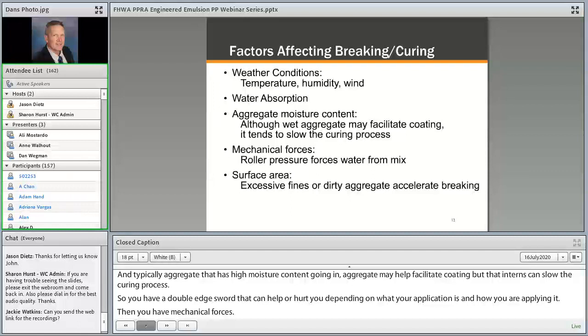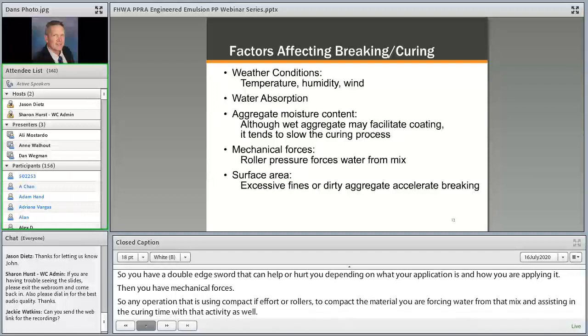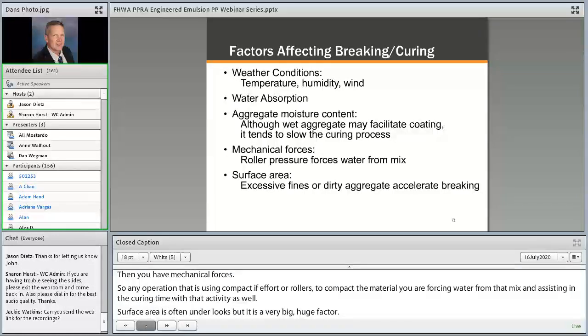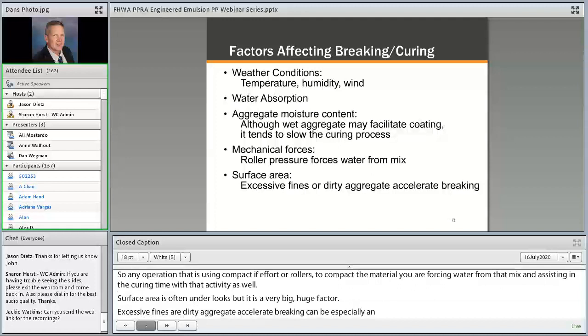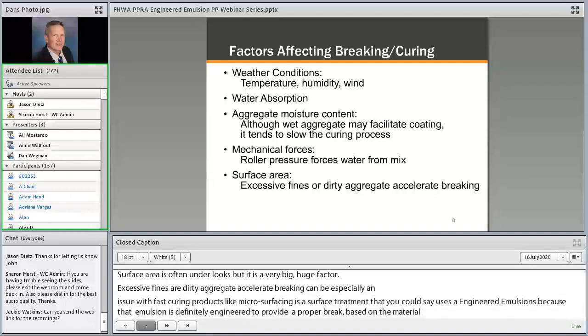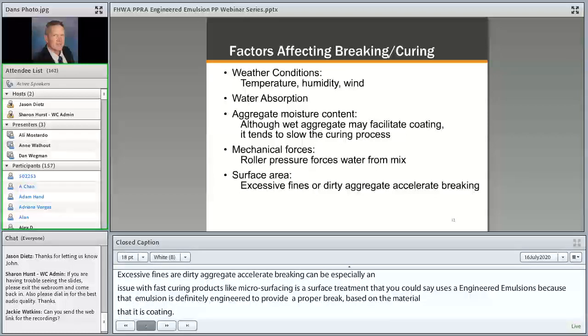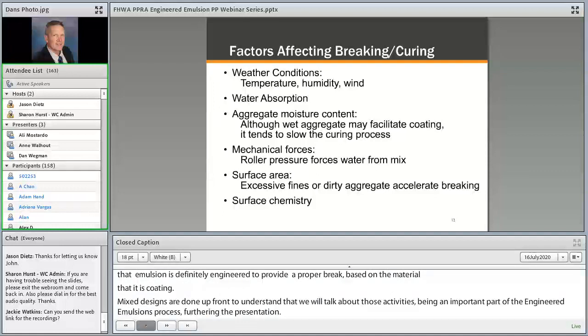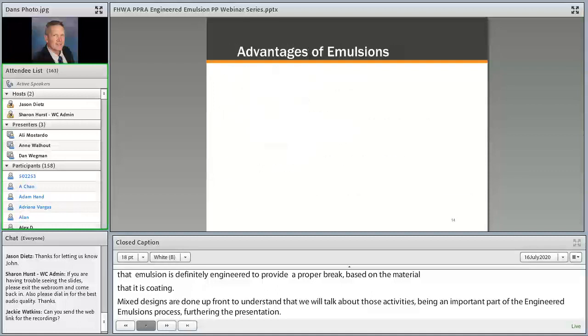Surface area is often overlooked, but it's a very big, huge factor. Excessive fines or dirty aggregate accelerate breaking. That can be especially an issue with fast curing products like microsurfacing, a surface treatment that you could say uses an engineered emulsion, because that emulsion is definitely engineered to provide a proper break based on the materials that it's coating. Mix designs are done up front to understand that, and we'll talk about those activities being an important part of the engineered emulsion process a little further in the presentation. And then surface chemistry, that whole aspect of being able to use chemistry to drive out moisture from the product is a huge factor as well.